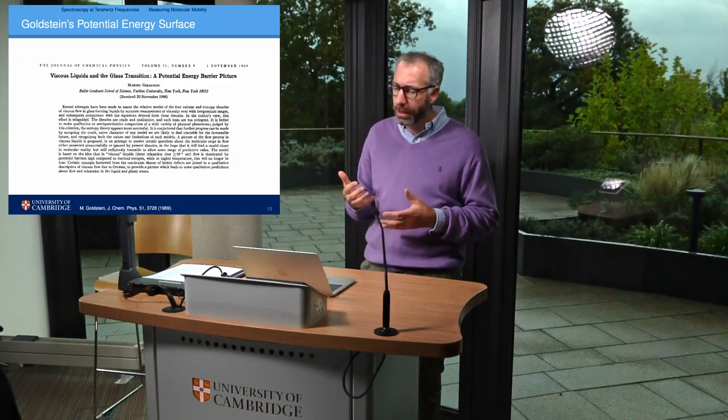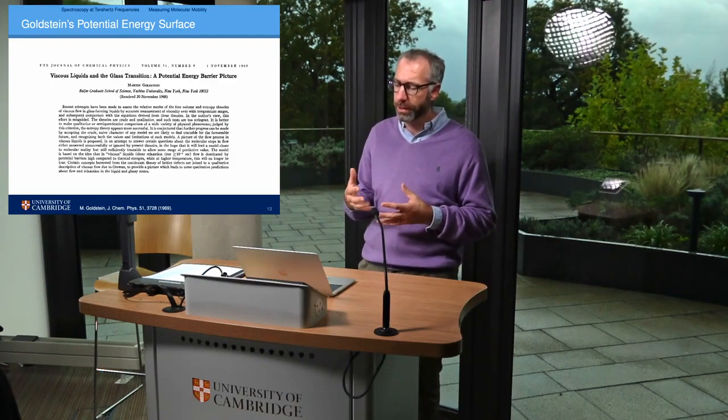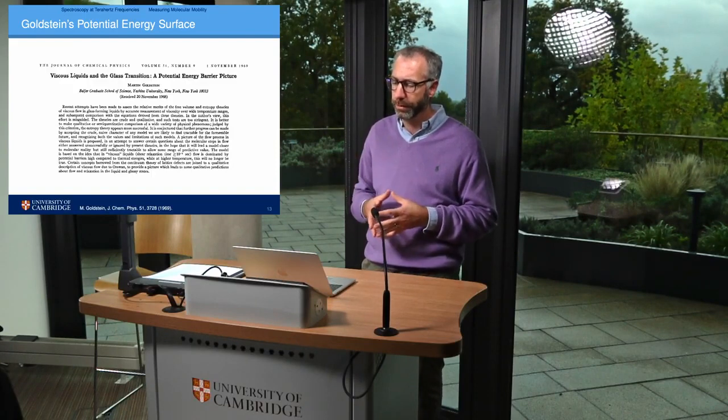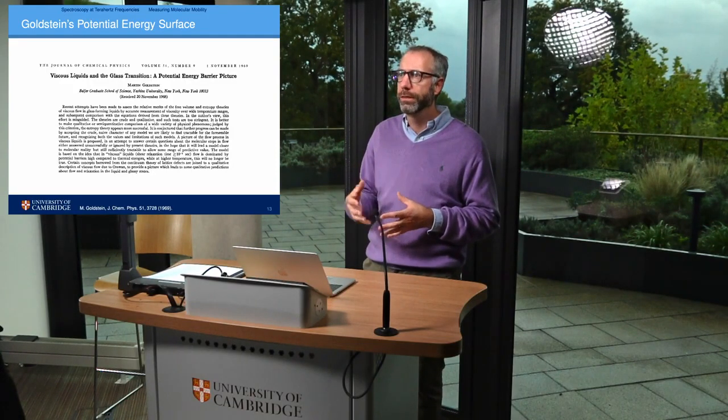In this paper, Goldstein outlines how the underlying shape and structure of the potential energy landscape determines the dynamics in disordered molecular materials, which explains the frequency independence of the observations. He argues that the molecular motions at low temperature are dominated by the existence of potential energy barriers that are large compared to the available thermal energy, and hence molecular conformations are locked into their glassy state. When sufficient thermal energy is available to overcome those energetic barriers, localized motion is possible, which then becomes a precursor to the primary glass transition at high temperatures.